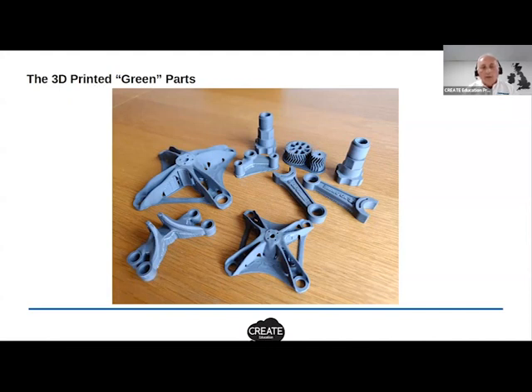But this is just one particular type of debinding. There are different types of materials around, sometimes using other types of binder. For instance, there are materials that use a binder that can be dissolved using acetone. That's a more chemical kind of extraction than the catalytic extraction for these materials. There are some interesting materials around. The stainless steels are the ones that are all programmed and dialed in for you to pick up and use. But if you're an education user and you want to explore some other materials, things like Inconel, tool steel, copper, talk to us at Create Education, because we've got some insights into those different materials should you want to experiment for yourself with something other than stainless steel.